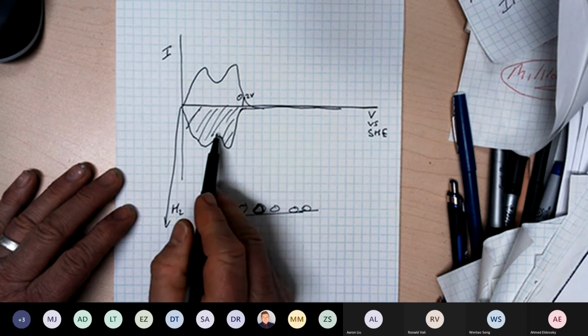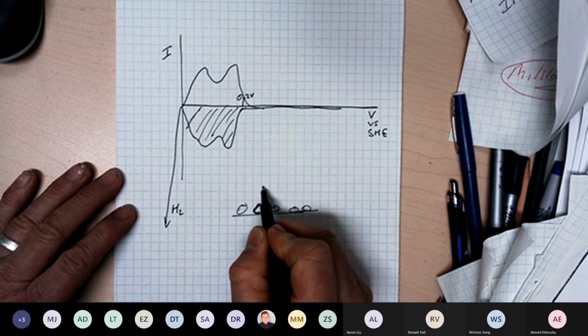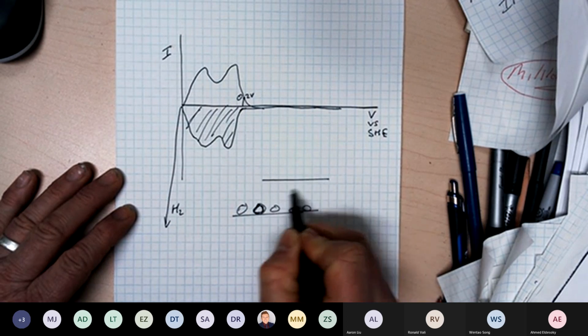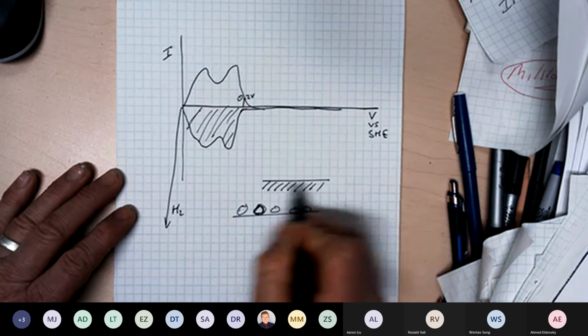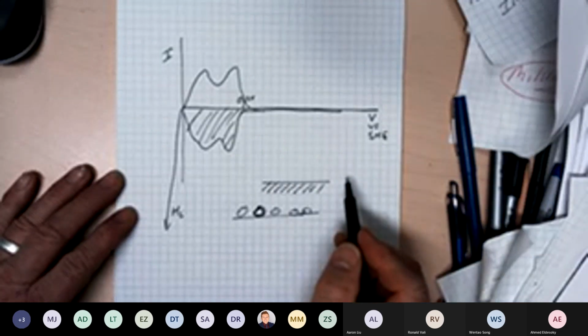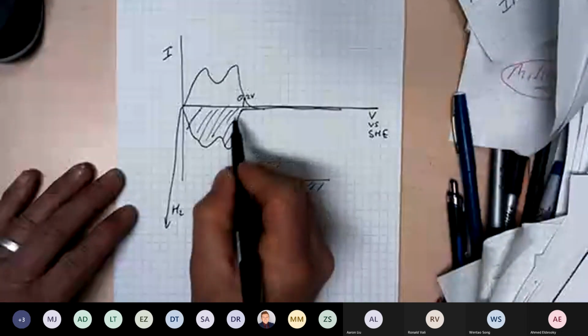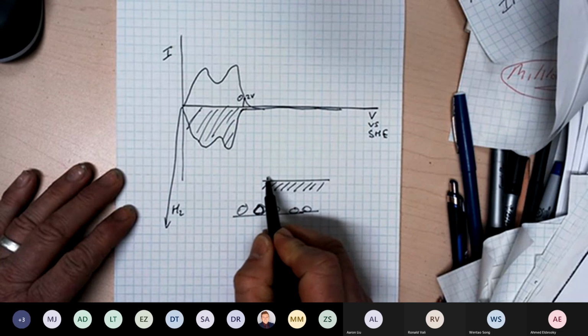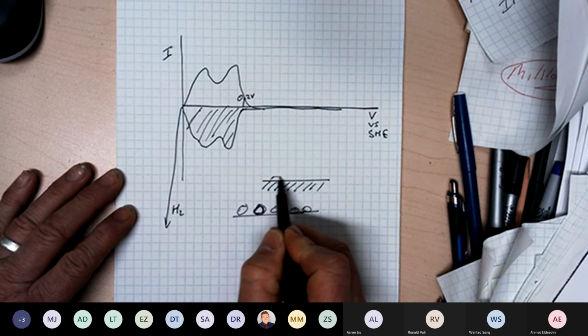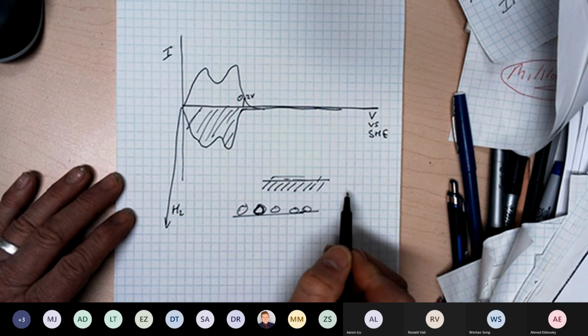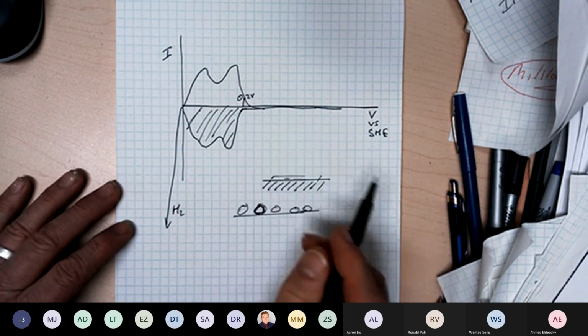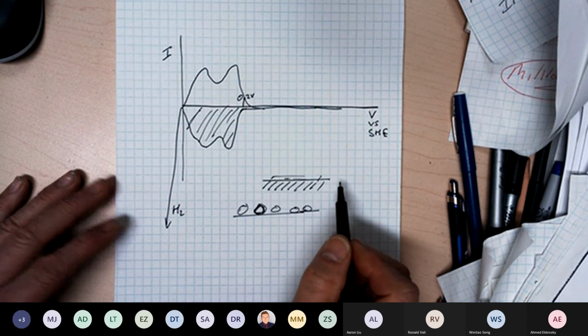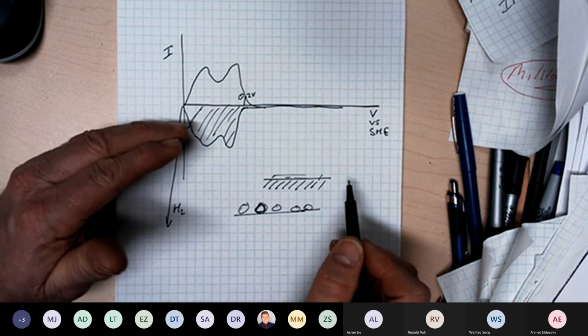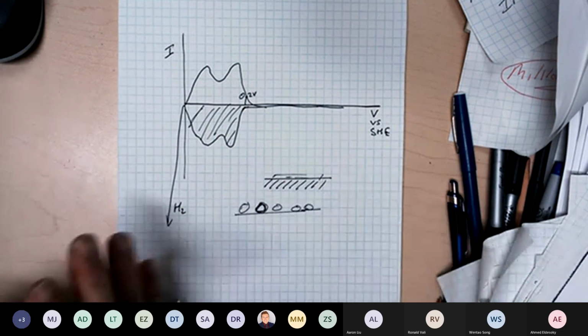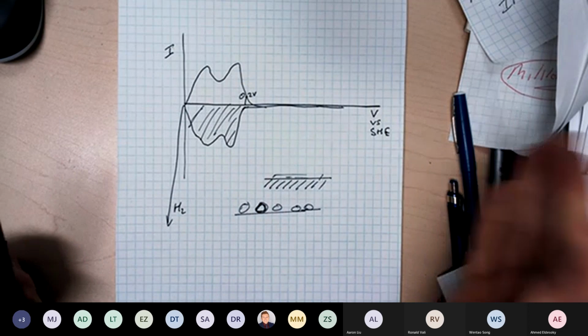So how do you figure out exactly what the surface area is? Well, you take a polished platinum surface, polished atomically flat, and in a rotating ring disk experiment, you do exactly the same experiment, and you measure the size of this bump. And then you know what the area of this bump is compared to 1 centimeter squared. So it's actually a simple technique that you can do right in the fuel cell itself. So you can track what's happening to the catalyst in the fuel cell itself, by stopping the fuel cell operation, running argon on the positive side and hydrogen on the negative, and doing one of these sweeps.